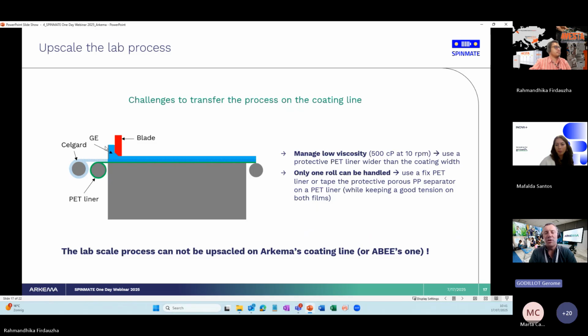The problem is the solution that we are using, as I said earlier, has to be very low viscous, roughly 500 centipoise, to impregnate well the porosity of the porous PP. And this means that it will not only impregnate the PP separator, but it will also spread all over the coating line. So it's not acceptable, and we have to protect it from the low viscous solution. So two options, using a PET liner. First option, a second roll with PET liner that will go with the Celgard and protect the coating line, or a fixed one if possible, just to protect the coating line from the solution.